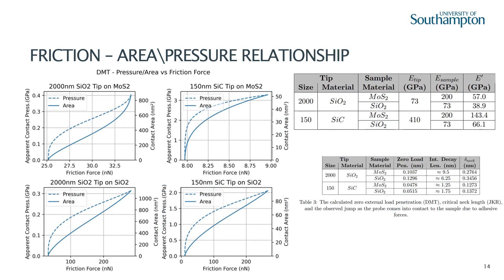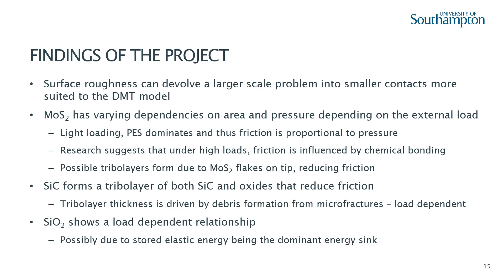These exact relationships were derived and presented within the report. Consolidation of additional research and peer-reviewed experimentation further supported this conclusion. Limitations of the DMT model present the contact area as a singularity as it decreases to a point contact, which occurs as the external load approaches a critical pull-off force. This is due to the DMT model being derived using the assumption that the contact stresses dwarf the adhesive stresses present across the body. From the DMT model's provided friction-area and pressure relationships, as well as considerations of previously published research, some assumptions were made as to the driving forces behind friction and whether the simplified models could be used to model friction appropriately in 2D materials.